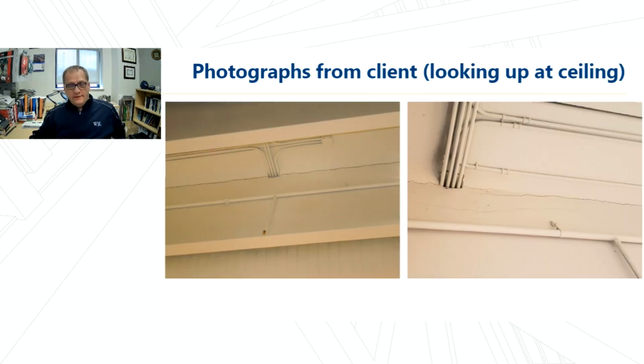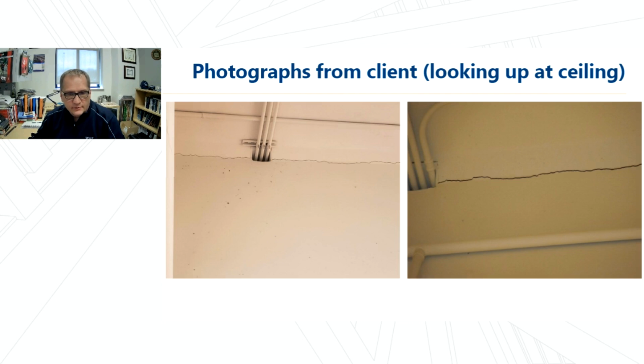So we got these pictures from the client, and we took a look at them and saw these cracks. We're looking up at the ceiling in these photographs, with some cracks at the fillet shown on the left photograph. On the right photograph, we've got some cracks at the fillet and on the face of the stem of the double T. We got a couple more photographs here, again showing cracks along the fillet. Based on these photographs, we would guess that these cracks are fairly large. We don't have a scale, but we have an indication of some pretty wide cracks along the fillet.